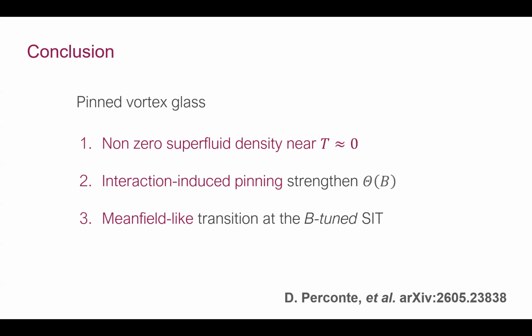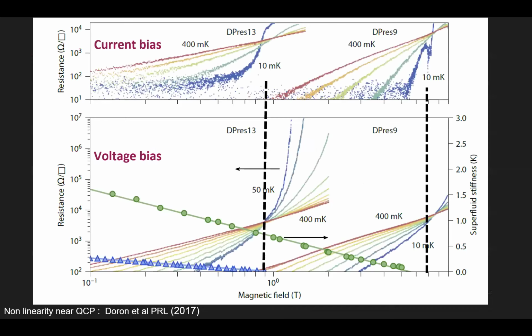Because we had a similar observation some years back, where we saw that the coherence peak in the spectra actually vanishes exactly at the same point. You are aware, because you are in the field, that if you do tunneling, you still have the same gap that goes into the insulator. There is a lot of evidence that electrons are paired in this insulator. The nature of this insulator is a big question. People even think that it might be a beautiful platform for many-body localization, for instance. I'm just stating that what happens before was just not known.